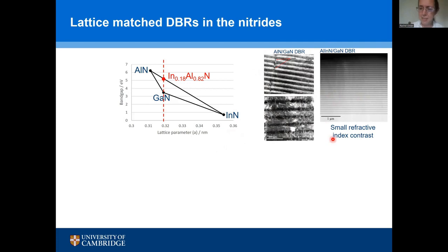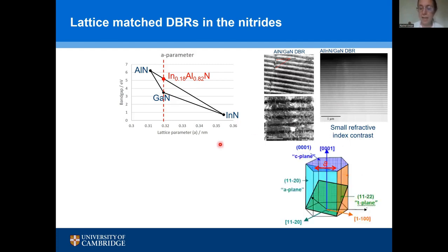It's not the best solution though, because aluminium indium nitride actually has quite a similar refractive index to gallium nitride. So you need an awful lot of layers to get high reflectivities, because you need large index contrast really for strong reflections. Okay, but all of that is reliant on growing on this polar C plane.